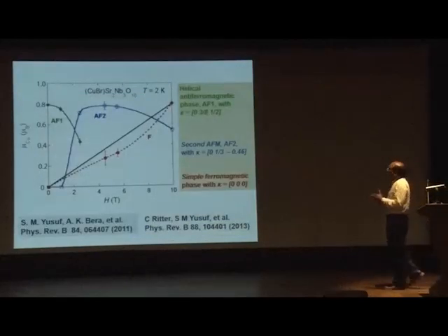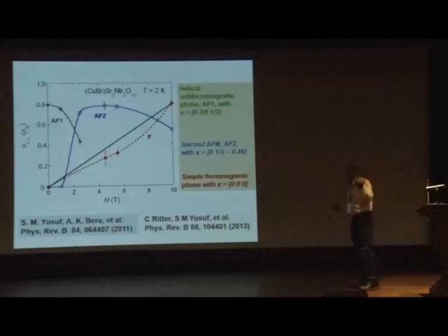And when we extended this study under magnetic field, that was under zero magnetic field, that was the ground state. Okay? Under external magnetic field, when we plot the ordered copper moment in Bohr magneton units, see, we get 3 phases. This is the ground state, which I just showed you, the spiral structure, that is the antiferromagnetic 1 spiral structure. But above this magnetic field, it goes to a second magnetic phase, that is antiferromagnetic 2.